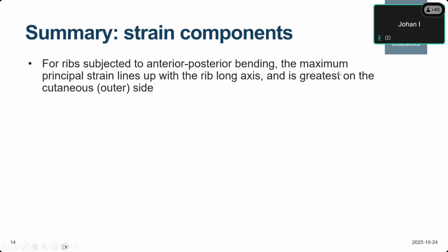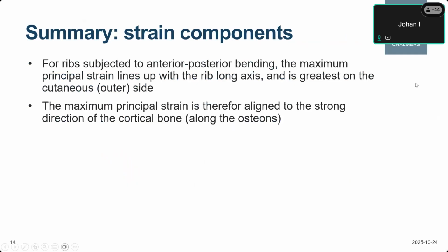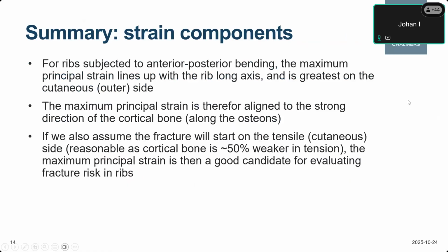Okay, so let's summarize the strain components here. If ribs are subjected to anterior-posterior bending, the maximum principal strain lines up to the rib long axis, and it will also be greatest on the cutaneous, or the outer side. The maximum principal strain is therefore aligned to the strong direction of the cortical bone along the osteons. And if we also assume that the fracture will start on the tensile side, the cutaneous side, which is reasonable, as the cortical bone is about 50% weaker in tension or 50% stronger in compression, the maximum principal strain is then a good candidate for evaluating fracture risk in ribs.